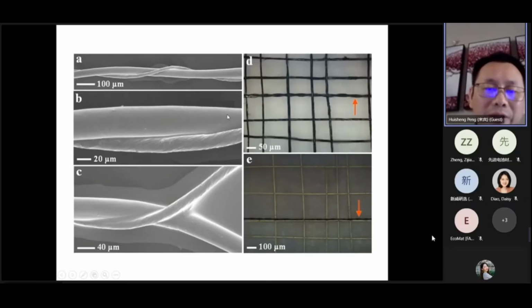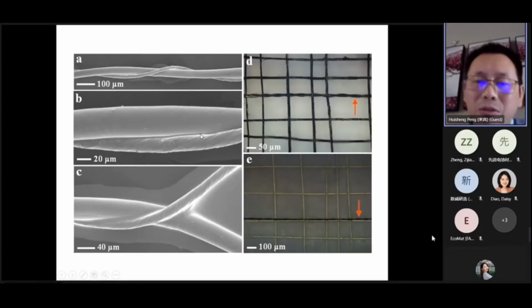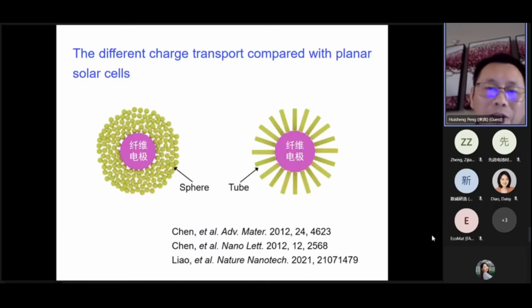So here we choose the carbon nanotube fiber. It's very flexible as one fiber electrode. And here the other fiber electrode can be carbon nanotubes or other fiber materials with the active layer on the surface. So you can see the interface is very good. We get this fiber dye-sensitized solar cell, and can weave it together or weave it with other chemical fibers. And these fiber solar cells have some very unique properties. Here I give you several examples.